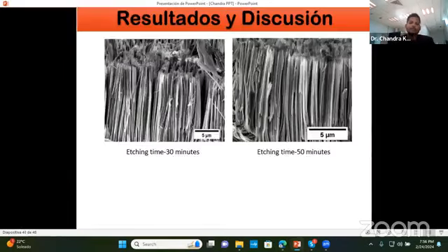See here, the result is quite interesting. This is for 30-minute etching time and 50-minute etching time. Here I didn't add 40 minutes. We also have 20 minutes, but silicon nanowire has formed for 30, 35, 40, 45, and 50 minutes. After 50 minutes is the saturation point. The nanowire is broken and divided into different parts. So this is straight and well aligned, vertical.